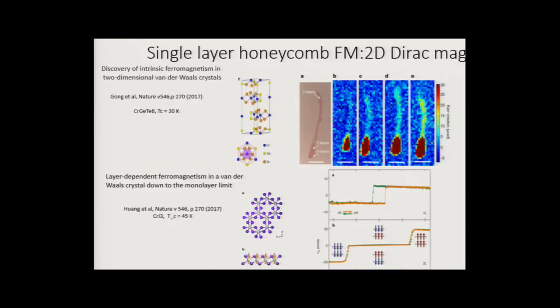I point out that there is interesting work coming out of MIT and others where they looked at exactly a single-layer version of this honeycomb ferromagnet. And so I would say that the same Dirac magnon behavior we see in the bulk will be present in these two-dimensional honeycomb ferromagnets. This work was published very recently, back-to-back in Nature, looking at the ferromagnets.